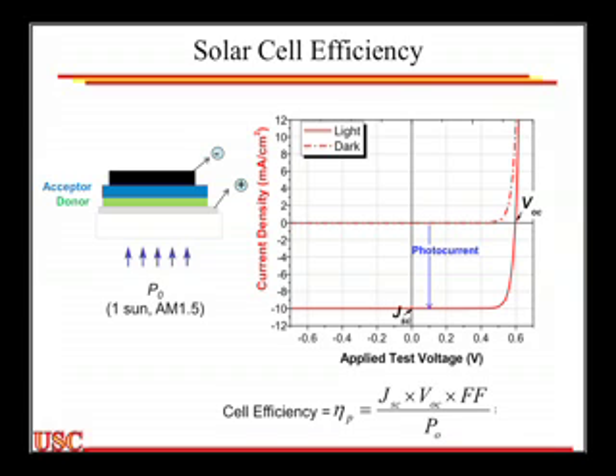Those are two important parameters. But the parameter that people worry the most about is the efficiency of the cell. The efficiency of the cell, which is eta, is simply the ratio of the maximum power to the incident power. So it doesn't matter what was absorbed, it's just how much power you get out versus the power you put in. And the power out is easy enough to get. If I take the product of the current and the voltage, I get the purple curve I show here, and if I go to the peak of that, that's the maximum power I can get out of the cell.